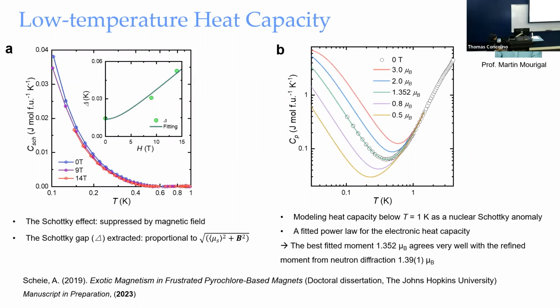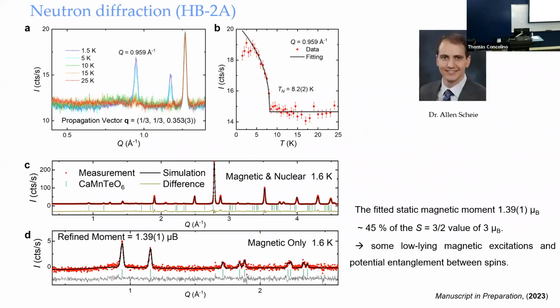And we look at it a little bit deeper by using the model built by Alan, also a friend of mine. We overlapped at Johns Hopkins. So here is the heat capacity as a function of temperature. We model this below 1K with the nuclear Schottky anomaly, and then fit a power law for the electronic heat capacity. And here is the result, you see it fits nicely with 1.352 μB, which agrees very well with the refined static moment from the neutron data that I'm going to show you right now, in the magnetic ground state.